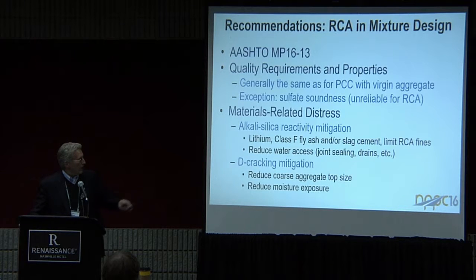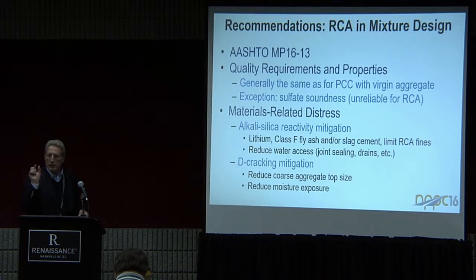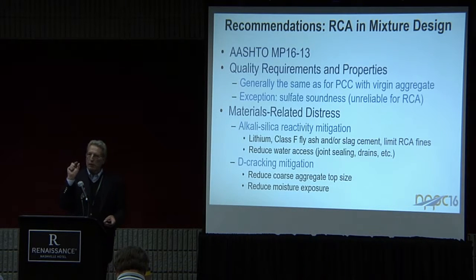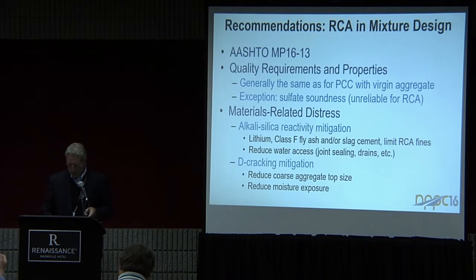Adding Class F fly ash, slag cement, limiting the amounts of fines, again cutting the surface area back, and then making sure we've got drains and joint sealing to keep the water out of the system, because ASR, like D-cracking and many other distresses, needs water to help kick things off. Same thing for D-cracking. Reduce moisture exposure, and also cut the aggregate top size back so that if it does have a little bit of expansion capability, it's doing it over a smaller particle size, which is not as disruptive. Been very successful in general with reducing coarse aggregate size down to 3/4 inch minus.